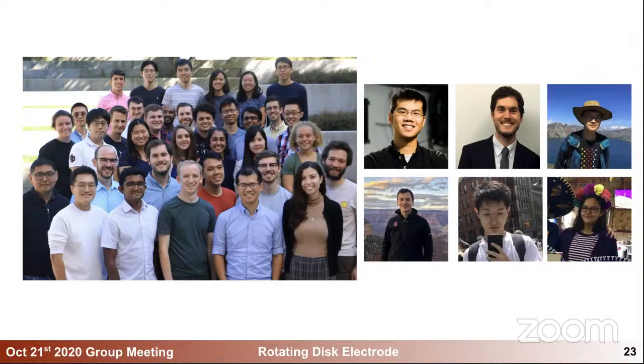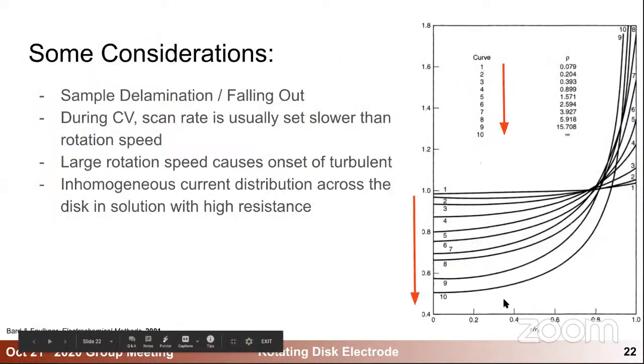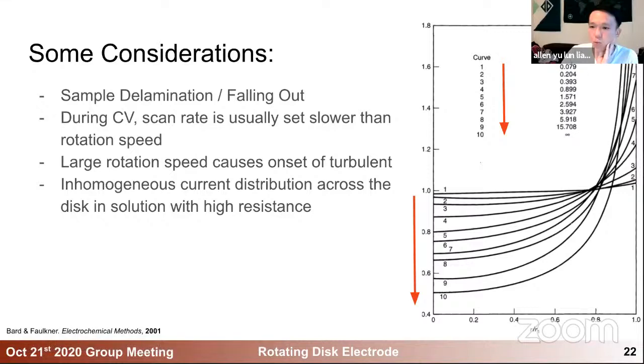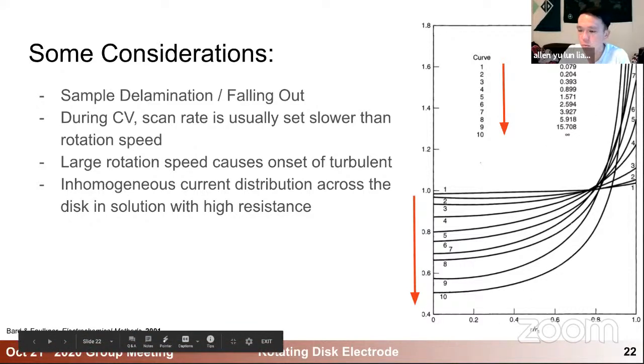Yeah, Alan, what is... I guess it's dimensionless, for the slide right before this where you're showing the resistivity of the electrolyte versus the current distribution? Oh, right, yeah. This rho is dimensionless. It's a ratio between the charge transfer resistance at the denominator, and the electrolyte resistance in the numerator. So if the rho value is small, meaning that the electrolyte resistance is really small, it's pretty much homogeneous across the disk. If you go larger and larger, theoretically if your electrolyte is just not conducting at all, then you have a really inhomogeneous distribution of the current across the disk.